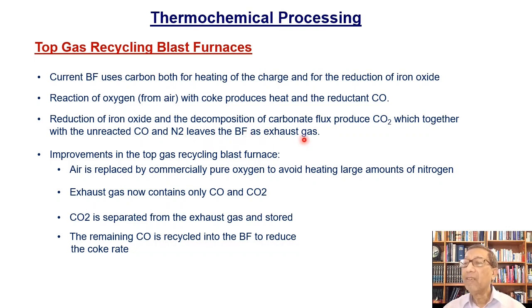So the improvement that we are thinking about in the top gas recycling blast furnace is to replace the air with commercially pure oxygen to avoid heating large amounts of nitrogen. That will certainly reduce the energy requirements. And then the exhaust gas, when we don't have any nitrogen, will contain CO and CO2. And CO2 will be separated from the exhaust gas and stored for other usage.